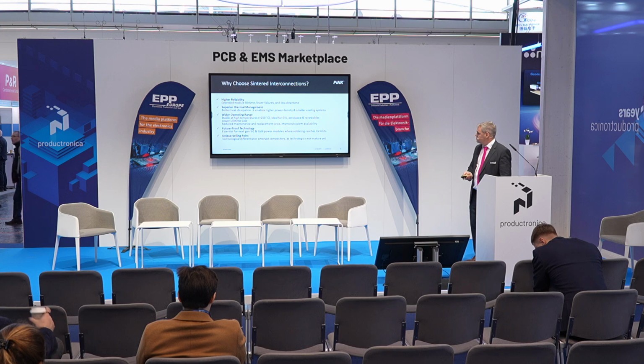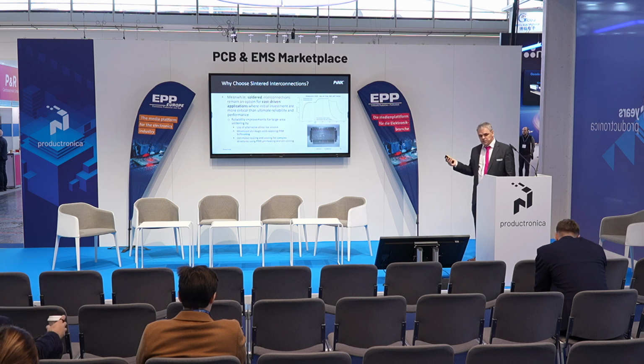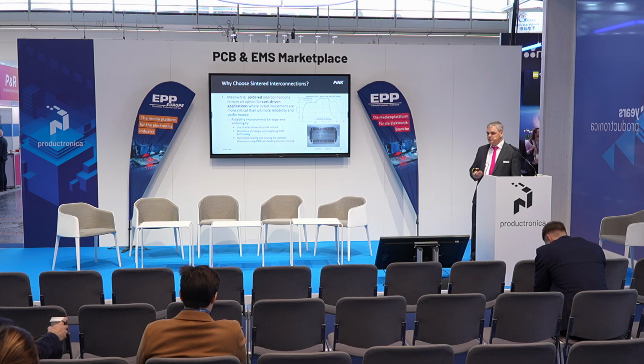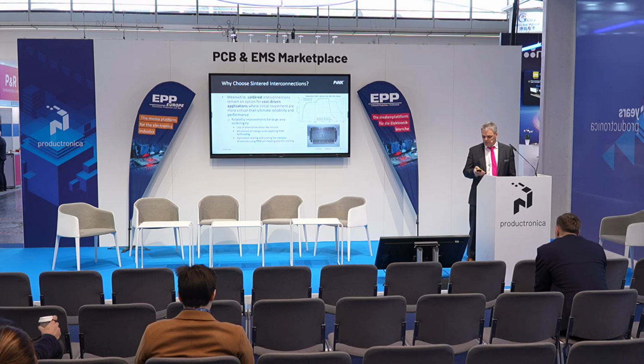Another point is, to me, that it's a technological differentiator because it's something unique. Not everyone can do a sintering of a molded package to a cooler today. That is not so easy. It's a little complicated. You need to know some of the details, so it's not mature. Of course, Mr. Feo also referred to that. A lot of things are done on solder in order to push the limits. For instance, you introduced indium as an alternative. We can also reduce the shrinkage voids on large area soldering to make such devices longer living, and we can have optimized structures or devices for perfect heating and cool down, in order to minimize the stress created inside that interconnect during manufacturing.